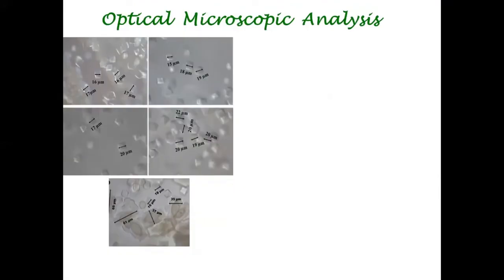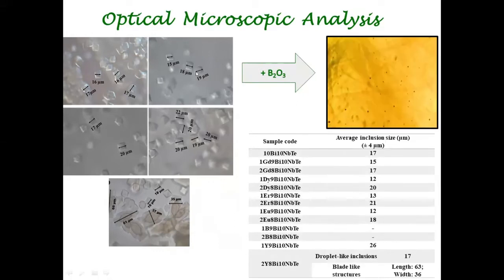And again, we see these inclusions, but the inclusions are of smaller size, about 20 microns. You can recall that in strontium telluride systems, the size of the inclusions was almost 700 microns, that means close to 1 millimeter. And you could see some of the inclusions even with the naked eye in the case of strontium tellurides. But here the size of the inclusions is small. If you add B2O3, which is a very good glass former, the inclusions disappear and we see only the glassy phase, the formation of the glassy phase.